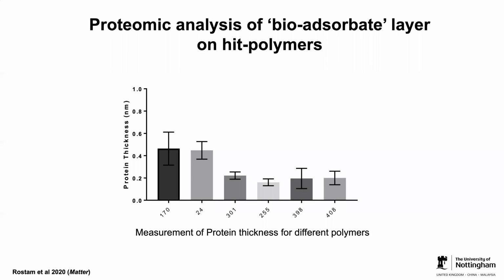And for a number of our hit polymers, the polymers that were able to promote either pro or anti-inflammatory responses, we looked at the bio-adsorbate layer on the surface of these polymers, because our working hypothesis was that the reason these polymers are able to differentially influence cell behavior is because they adsorb different proteins from the media at different levels and different combinations of these proteins on the surface. And that's how cells respond to these different bio-adsorbates, and they acquire different phenotypes.